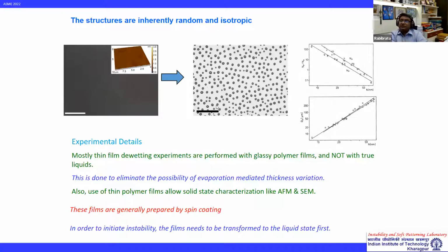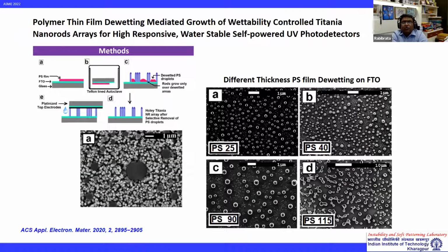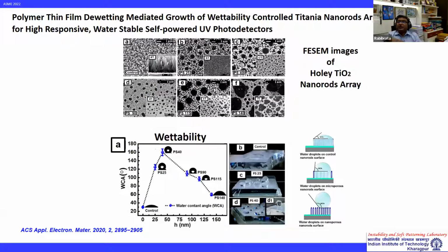And people have used these types of dewetting-mediated structures. There is an ACS Nano paper in 2011, where they enhanced the photoluminescence of some material. Chiara Neto from Australia has been using these structures for water harvesting. And even from our group, we used some of these structures as a mask for growing titania nanorods, and with which we could modulate the wettability of this nanorod array by controlling the porosity of the array on the surface, by means of where these dewetted droplets were. So that allowed us to make a holey titania nanorod array, which led to structural hydrophobicity.